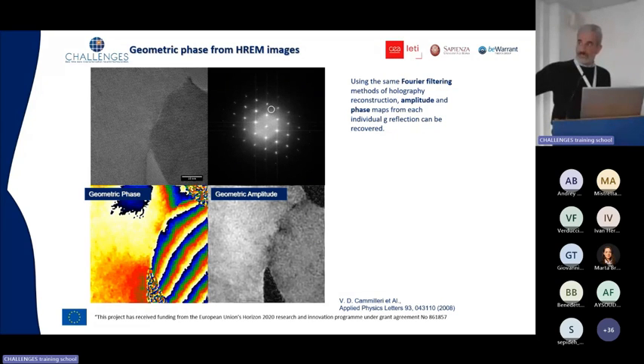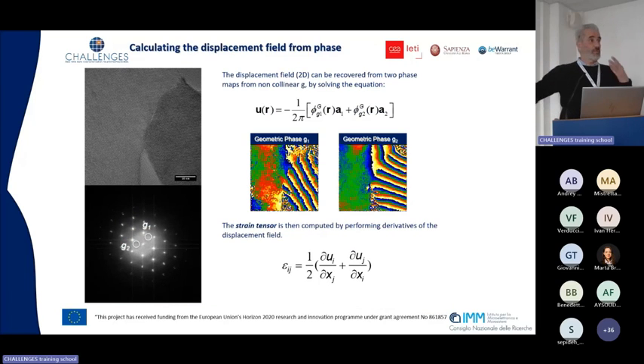This is how the phases, the position of the silicon germanium atoms, differ from the silicon reference with the distance. So it is a method to detect what the lattice parameter of the silicon germanium is. If you take one lattice spot and then a different one that we are calling G, this spot, this one and this one, you can combine them to extract a 2D strain map of your materials.